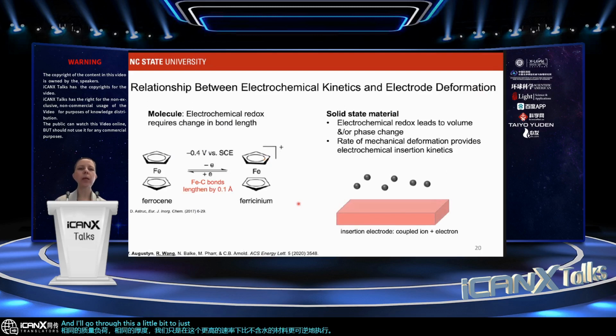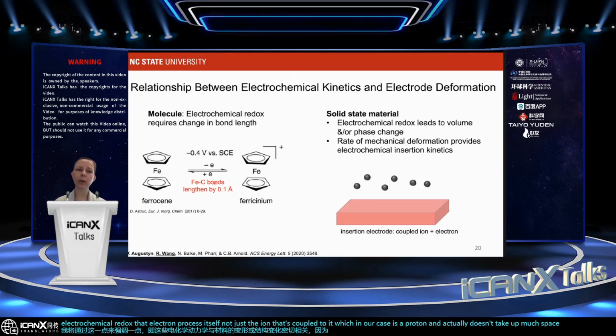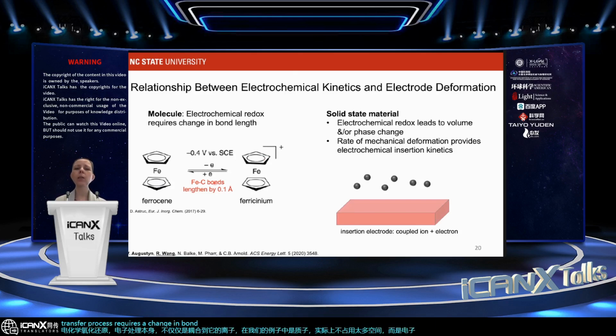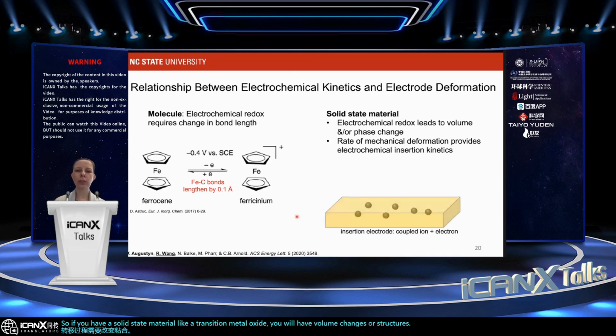to just emphasize the point, is that these electrochemical kinetics are strongly tied to the deformation or the structural changes in the material, because the electrochemical redox, that electron process itself, not just the ion that's coupled to it, which in our case is a proton and actually doesn't take up much space, but the electron transfer process requires a change in bond length. So if you have a solid state material like a transition metal oxide, you will have volume changes or structural changes that take place to accommodate the electron transfer and the proton insertion.